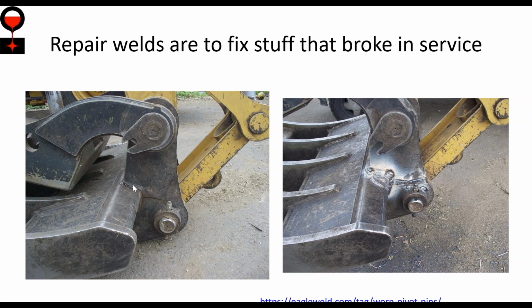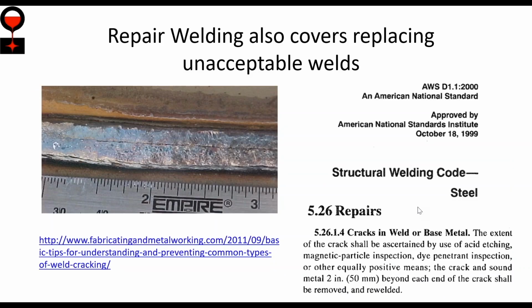So this is what a repair weld is. This cracked and I welded it up. Another use of the word repair welding, and this goes back to the 1920s, is if I weld it and it cracks, I have to grind out that weld and repair it. So if I look at the AWS D1.1 standard, there's a section 5.26 repairs where it identifies the requirements for